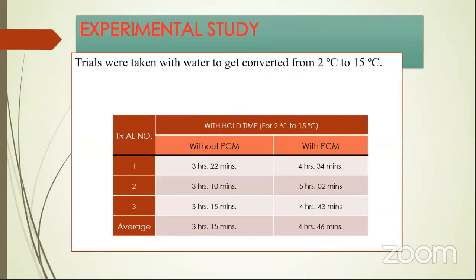And we did some study on that. The trials were taken with water being heated from 2 degrees Celsius to 15 degrees Celsius. And these are the results we got. So without PCM, this is the temperature range, 2 degrees Celsius to 15 degrees Celsius. Without PCM, it holds only 3 hours 22 minutes.